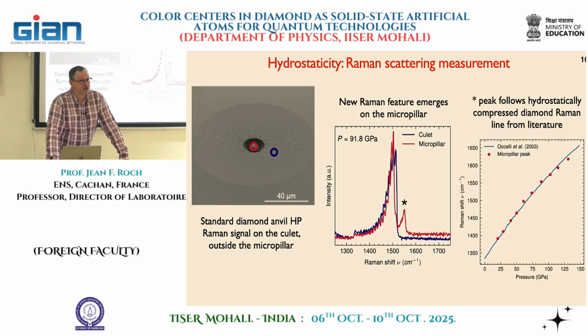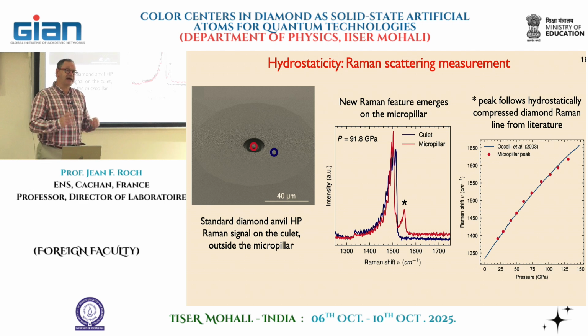And if we now look at the evolution of this small peak on top of the pillar as a function of pressure, it follows very well the dependence that was found in hydrostatic conditions for the diamond Raman shift. So this is the first evidence that indeed our pillar technique provides us a method to retrieve hydrostatic conditions.